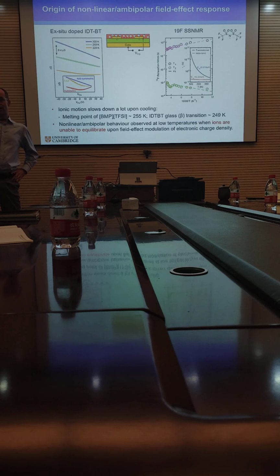But when you cool down the device to below 240 Kelvin, then you start to see this nonlinearity emerging and this ambipolar shape of the transfer characteristic builds up. So it has something to do with a process that happens between room temperature and 240 Kelvin. And what we think is happening there is that the ions are becoming frozen. So there's the polymer glass transition in that temperature regime, there's the melting point of the ionic liquid.